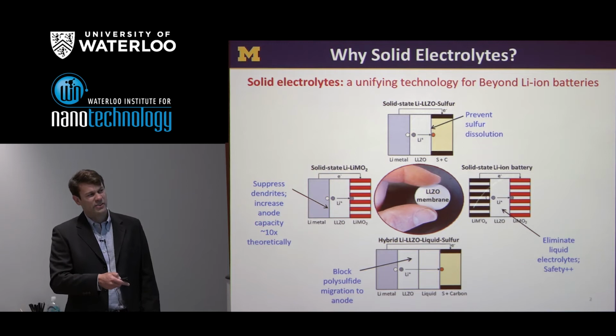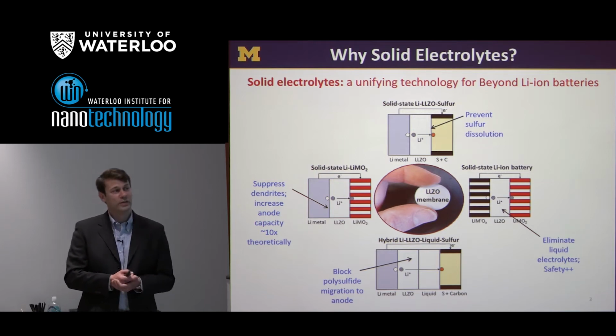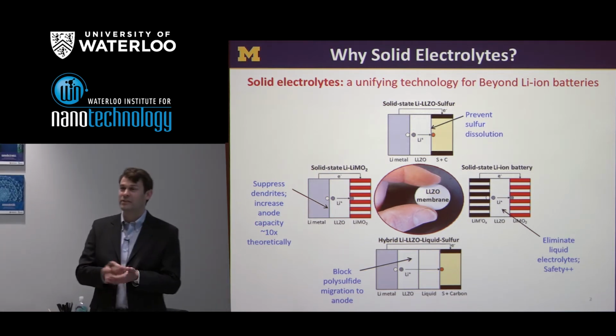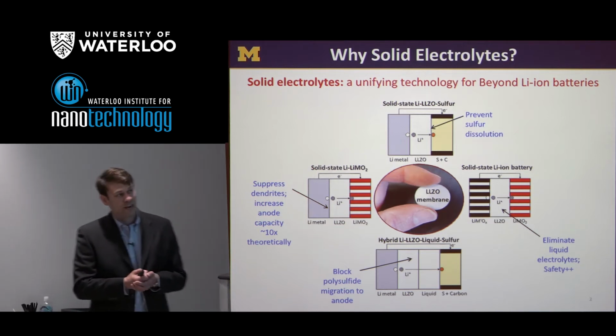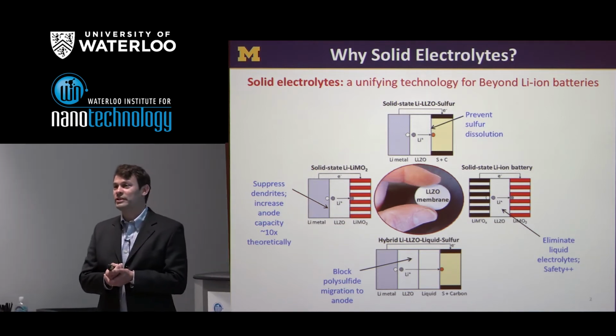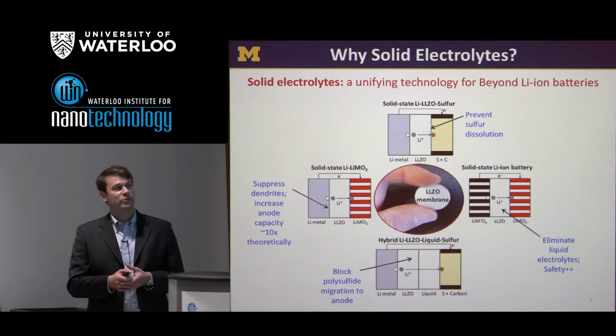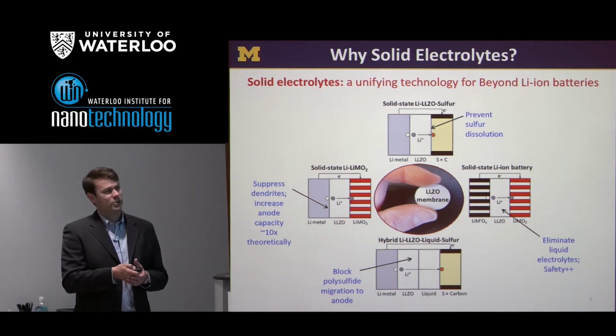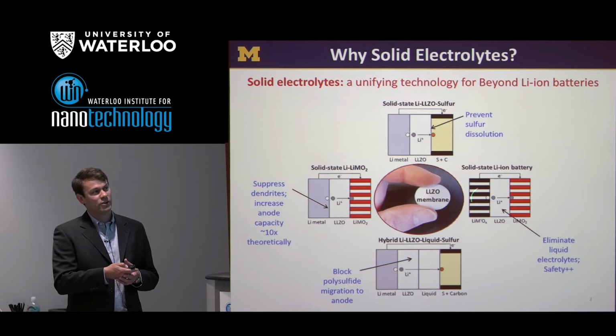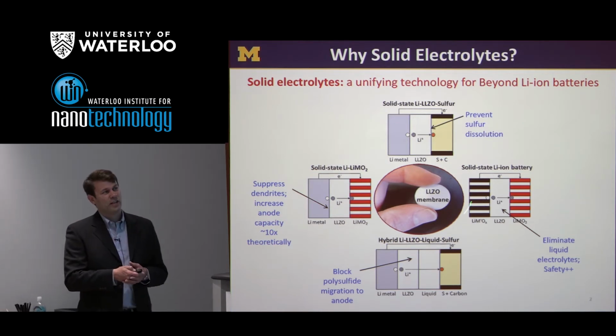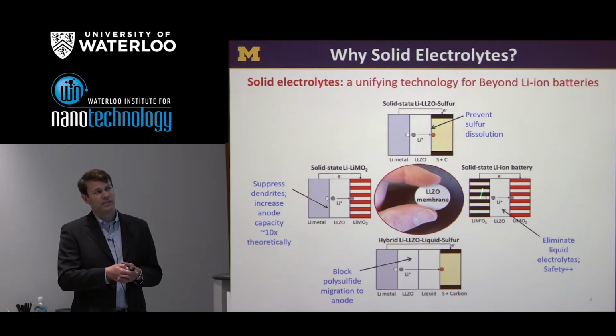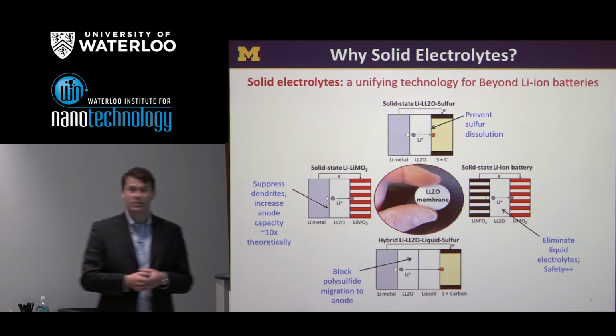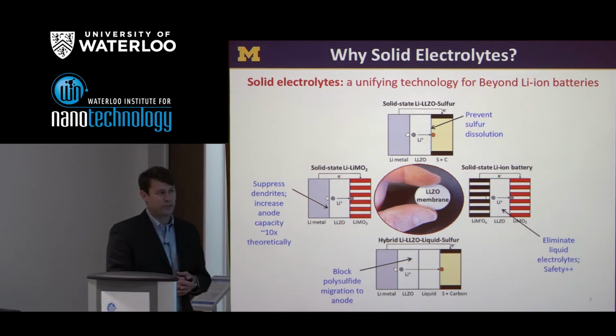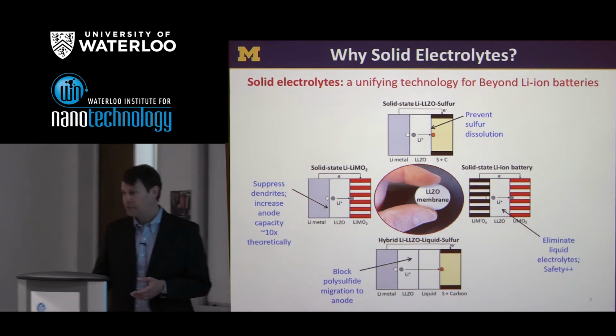Thinking about safety on the other side here, one thing you may know about these liquid electrolytes, in addition to the fact that they don't really help us with the dendrite problem, they're also flammable and volatile. So if we can get rid of those liquids, replace them with a solid, we have an immediate increase in battery safety. In fact, one could imagine an all-solid state battery where instead of using even lithium metal here, we had another intercalation host as an anode, LLZO or some other solid between them, and then of course another intercalation host as the cathode. So this would be a totally dry system, again, improving safety.